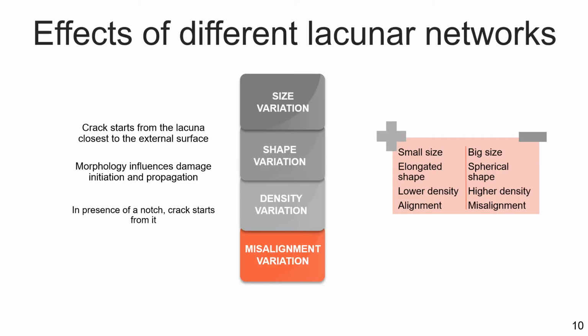Variations in size, shape, density, and alignment of the lacunar network are considered for the analysis. Small size and elongated lacunar samples show slower crack propagation. The same trend is visible in presence of a lacunar network characterized by a lower density and alignment with respect to the direction of the applied load.